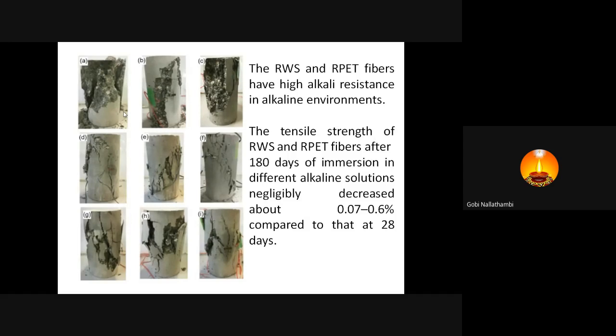One important finding is that it has a very high alkali resistance. The tensile strength of recycled woven sack waste and also recycled PET fiber after 180 days of immersion in different alkali solutions negligibly decreased, about 0.07 to 0.6% compared to that at 28 days. So there is not much change in the property of the material after the samples are dipped into alkaline environments or alkaline solution for more than 180 days.